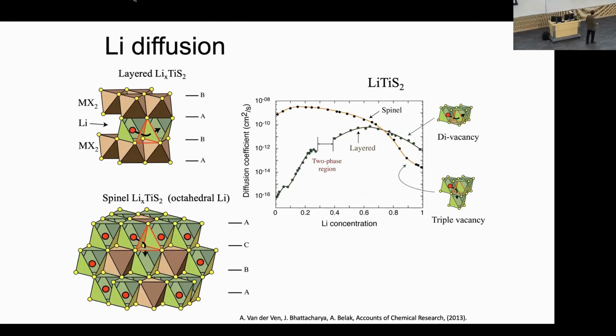And so I'll end with this, but this is just calculated diffusion coefficients. One is for a layered material. The other one's for the spinel compound for lithium. The exact same chemistry, TiS2, just a different crystal structure, vastly different diffusion coefficients as a function of composition. First of all, the diffusion coefficients change dramatically with composition by many orders of magnitude.